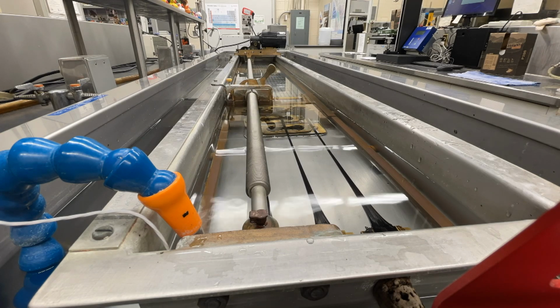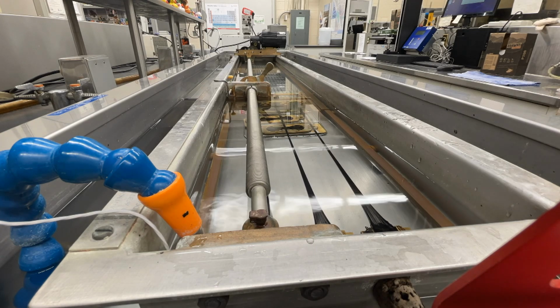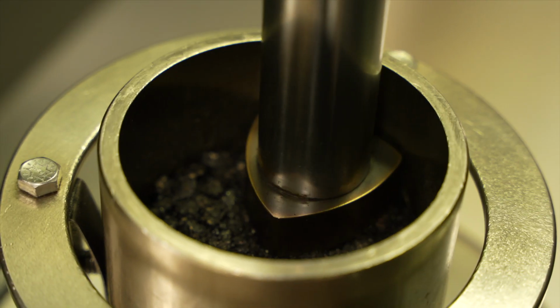One of the ways we test for that here in the asphalt lab for polymers, we'll fill a mold with asphalt and chill it down to 4 degrees Celsius, and then stretch it at 5 centimeters a minute until it ruptures. And those are just a few of the tests we do to ensure that we have the highest quality materials being placed on our roadway.